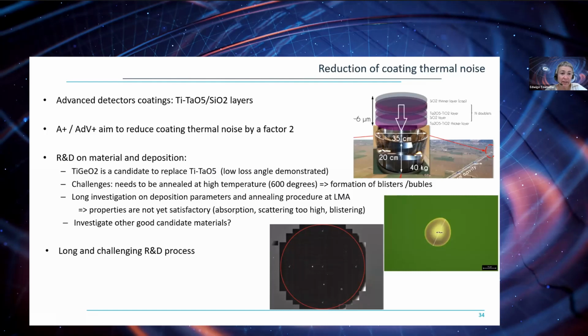The challenge is that there is a quite complicated deposition process, and it needs to be annealed at high temperature, and there are many challenges in this deposition process, and the coating can lose its good qualities through these processes. For example, we see now the formation of kind of bubbles in the coating, which we don't want because it deteriorates the quality. So there is a long investigation of all these procedures, and the properties are not yet satisfactory. The absorption is too high, there is too much scattering due to those blisters, and we are still investigating the possibility of using other candidates. So this is a long and challenging R&D process which is still ongoing.